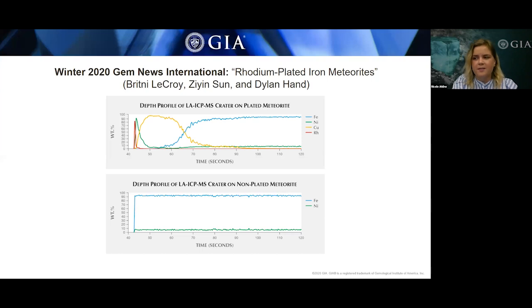So displayed in the figure is a chemistry comparison of the pendant versus a non-plated iron meteorite. Along the y-axis, top to bottom, is the concentration of these elements detected, with the x-axis representing the depth of the LA-ICP-MS as it drilled into the stone. So for the pendant at the surface, there are high concentrations. You can see, let me highlight it for you, right over here, there are these high concentrations of nickel, copper, and rhodium, and then they taper out to just iron and nickel, which are the only two elements present in the non-plated iron meteorite seen in the profile below.